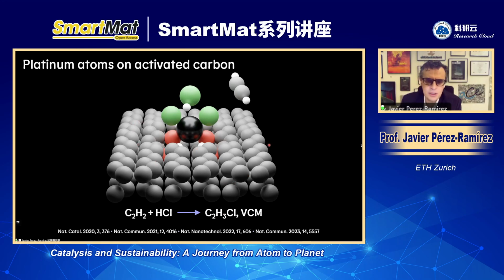And you see here the carbon structure. And this is the cavity and the oxygen atoms on the carbon where the platinum single atom is stabilized. And you can see that the platinum single atom has some chlorine, and it has some chlorine because it's prepared typically from chloroplatinic acid.